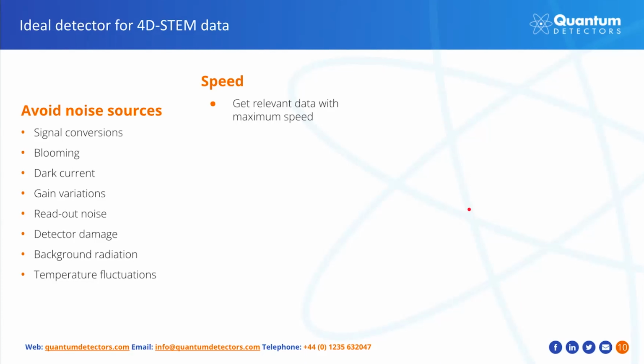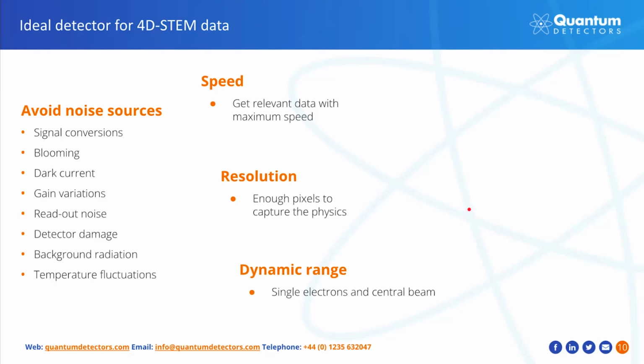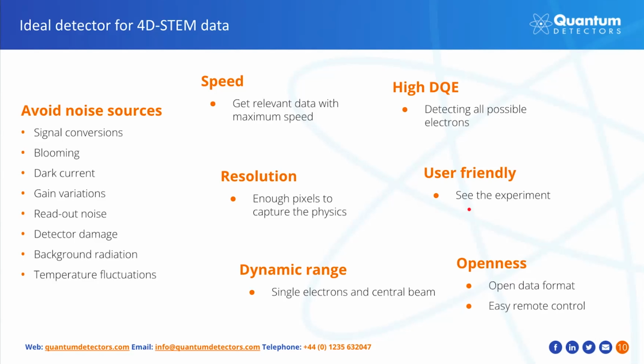On top of this, the detector needs to have sufficient frame rate to get relevant data with maximum speed. It needs to have high enough resolution to be able to capture the physics. It also needs to do it with enough dynamic range, so researchers are able to collect single electrons from the less bright areas of the frames, together with the very bright area in the center of the 2D diffraction image. The detector also needs to collect data with high efficiency, so we want to detect all possible electrons. It needs to be user-friendly, with means to view the experiments in real time. And last, it should supply the scientists with open data and a way to remote control experiments for maximum practicality.